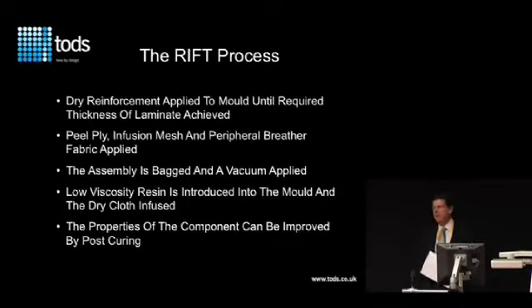Resin infusion under flexible tooling, there's a number of names for it. Basically, you lay up dry material into your mould, you bag it with a vacuum bag and the normal accessories. You apply a vacuum, and then you introduce low viscosity resin into the bag, and it goes through it and infuses. The properties of the component can then be improved by post-curing. And if you're careful, you can actually post-cure out of the mould, which has its advantages.